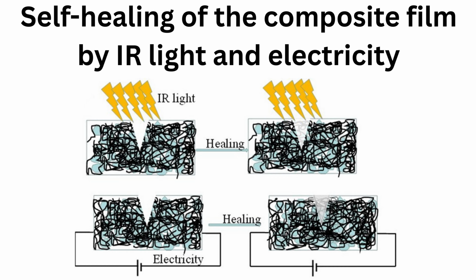The excellent infrared absorption and energy conversion/transfer capabilities of graphene allow the temperature of the GTPU composite film to rapidly rise close to its softening point, thereby enabling self-healing of the composite film through wetting, diffusion, rearrangement, and cross-linking of TPU chains, followed by solidification. In the electrically stimulated healing process of the composite film, the temperature also increases due to electrical energy being converted into Joule heating, thus promoting the self-healing behavior of the composite film.